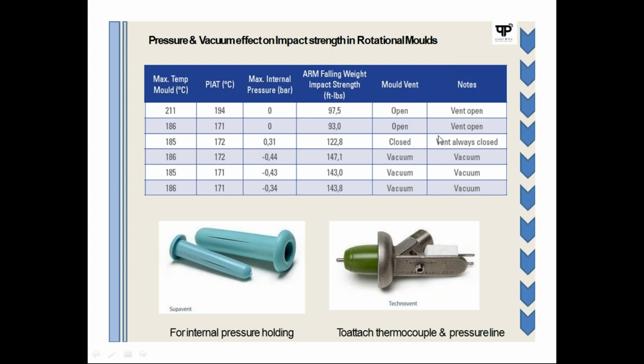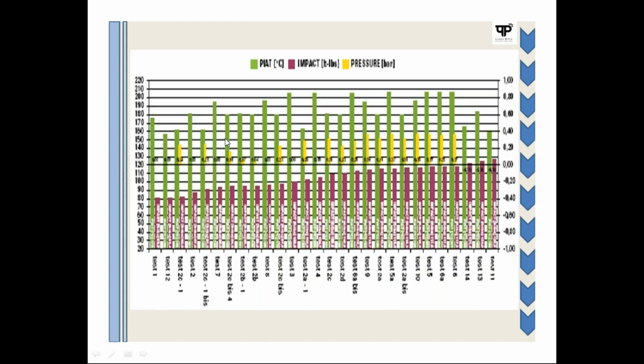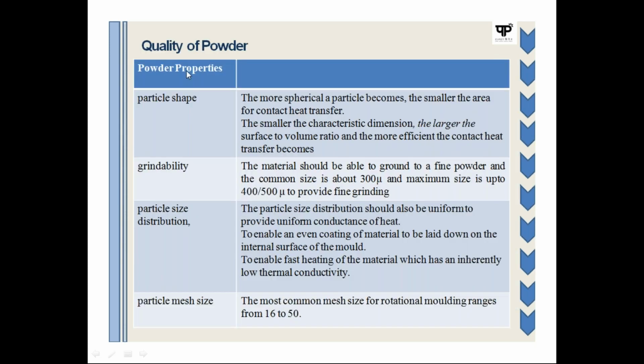So what I mean to say, this is the part where you can see the pressure and the vacuum effect, which you can find in the quality of the product, depending on the shape you are going to use. Now this is an entire profile using different permutation combinations. The quality of the product depends on the particle shape you are using. For rotomolding, the raw material is in powder form. Particle size means what size you get once you are pulverizing it, and depending on that particle size you can attain a good quality of the product. The more spherical a particle becomes, the smaller the area for contact heat transfer.